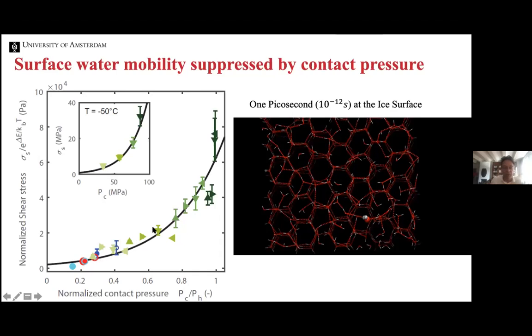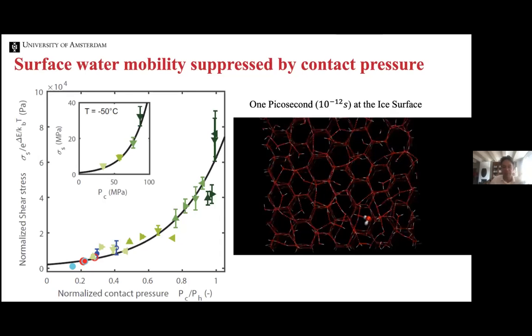So this line is actually the theory that predicts the pushing out of the layer of mobile molecules, and the data is from different temperatures, different pressures, or different normal forces and different roughnesses. So this is once again a proof that it's not just the water layer, it's really the layer of mobile surface molecules. And if your skate is too rough, you will push them out and it becomes impossible to skate.